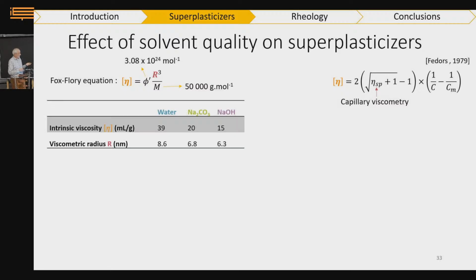And what do we see? Well, we see that indeed the viscosity depends on the solvent. The viscosity drops when I dissolve sodium carbonate in the water, and even more when I dissolve sodium hydroxide. I don't have the concentration used here, it's missing, I'm sorry. But the message is that the viscosity drops, and that means that also the radius drops, meaning that the blob tends to shrink. The quality of the solvent is degraded, as I said previously.